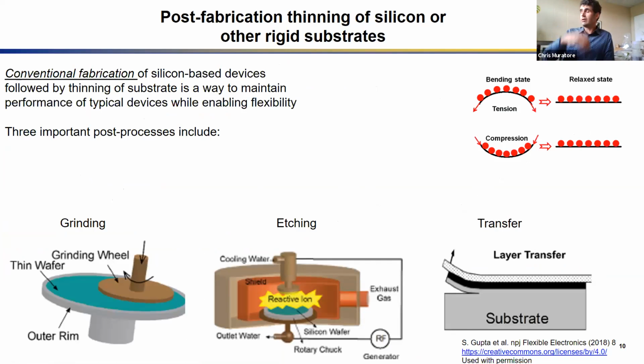So if making materials thinner is a way to get to flex, then how can we do it? There's a few ways. One common way is to just grind the material away. And so there's all kinds of commercial equipment you can buy to make silicon wafers be thinner, or any kind of wafer be thinner, and just build a device upon it. And that's kind of nice. If you get the thickness right, you can still use the structural aspects of silicon to deposit materials and grow your devices straight onto the substrate. You would have to do some grinding before you wanted to do etching, because etching's not quite as fast as grinding.